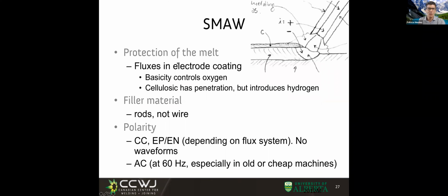And how do we protect the melt in this case? This is somewhat similar to a self-shielded flux core, right? It's the fluxes in the electrode that give the protection. But now we can have much more flux than we had in flux core arc welding. Before we could have a tube with a little bit inside. Now we can put outside as much flux as we want. And we can do so many things. For example, we can have materials that will give gas, so to some extent, we have somewhat of a shielding gas.